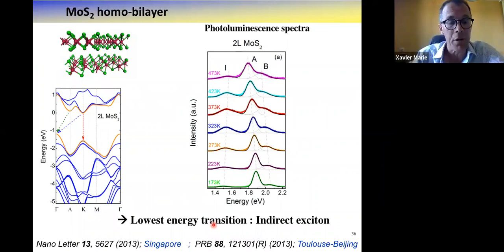So as I said in the introduction, MoS2 homo bilayer at the beginning, maybe you can say it's not so interesting. It has been known for a long time that it is an indirect gap semiconductor. Basically you have the dispersion curve, energy as a function of the wave vector, and the lowest energy transition occurs between a valence state in gamma and a conduction state either in K or in an intermediate value we can call Q or lambda. But anyway, this is an indirect transition.